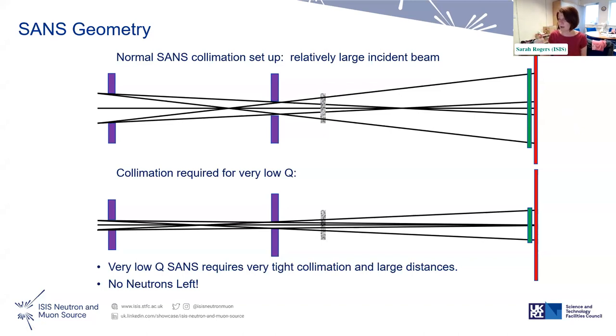And we have to have those in place to protect the detector. That's the only reason it's really there. But also it's where the direct beam is splattering. So you couldn't really pull anything out of that information anyway, even if it went onto the detector, there's no small angle scattering there. So the biggest objects we can see are determined by the size of that beam stop, because that's the smallest angle you can get to, the angle between the sample and the edge of that beam stop, basically.